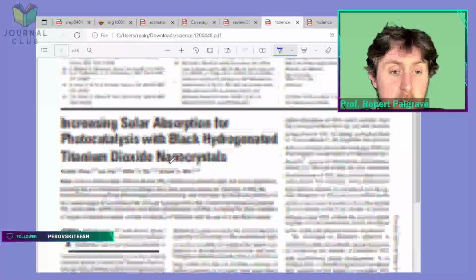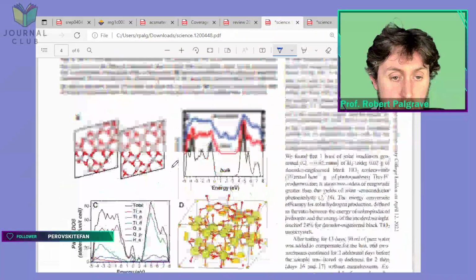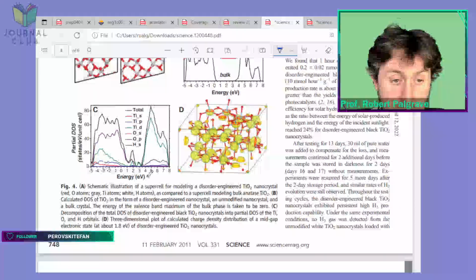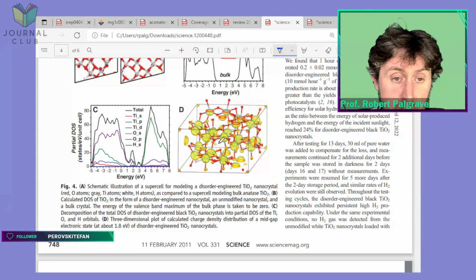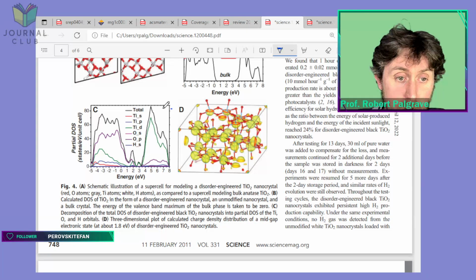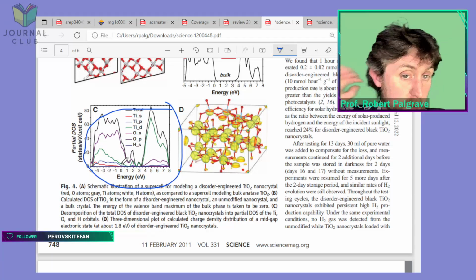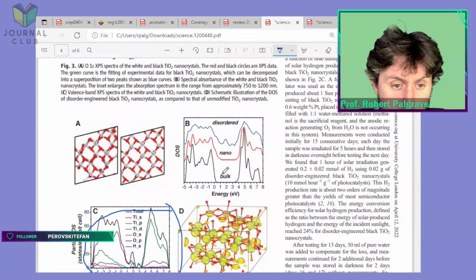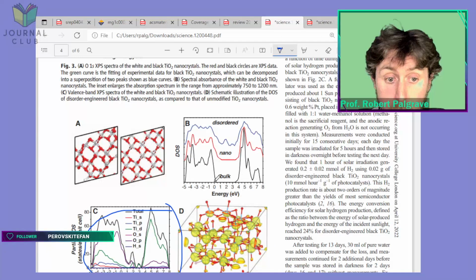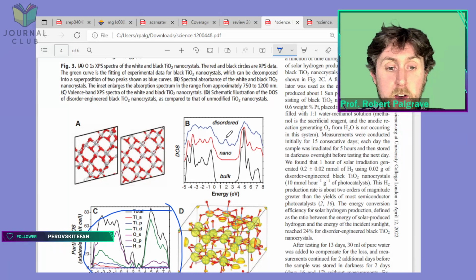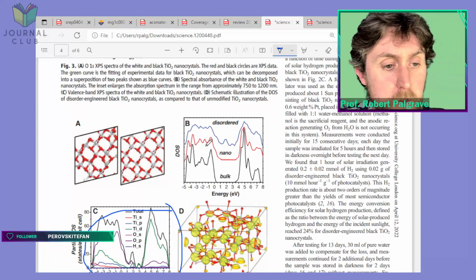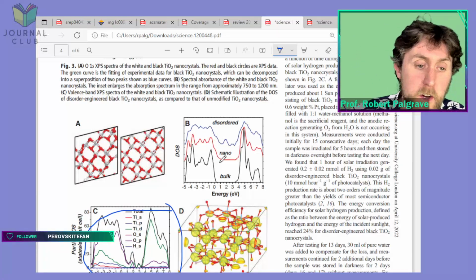So this is the kind of background to, I will just show you at the end a bit of characterization they did. They did a little bit of density functional theory, so they did some calculations on the material. I guess they just kind of plonked in the hydrogen where they think it might go, and they came up with this density of states here, which tells you about the energies of the electrons within the material, and compared that to the bulk TiO2 without any dopant, and you can see they have these extra features inside the band gap, which they can attribute some of the enhanced properties to.